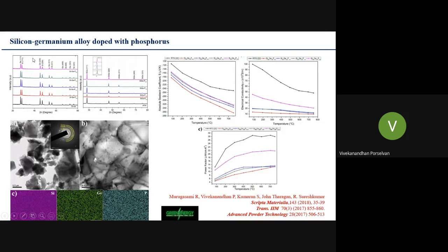And here is another case, a silicon germanium alloy doped with phosphorus. From the TEM image we can understand that we have a solid solution of silicon germanium of ultrafine scale with crystallites in the nanoscale. Here the black color is given. It corresponds to the radioisotope thermoelectric generator, which is currently being used in space. And this is the material we have synthesized, so we are able to get a power factor very close to this particular RTG.